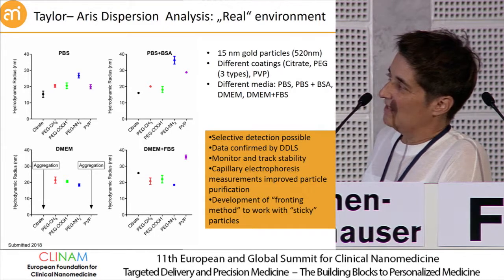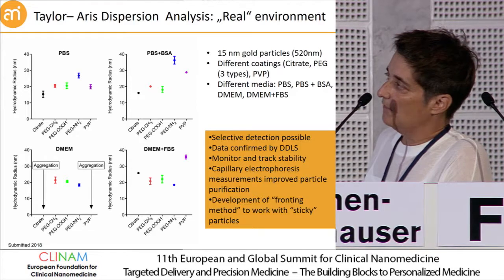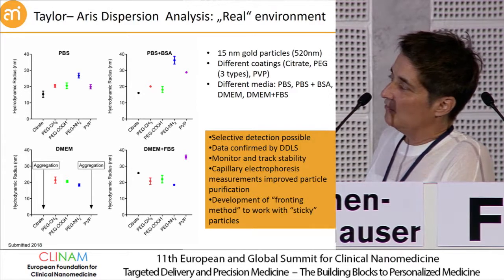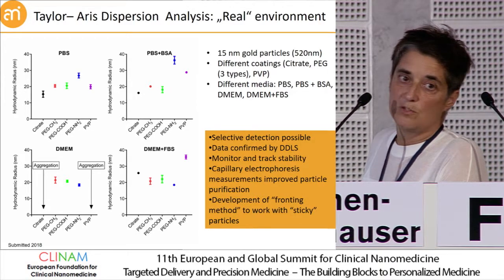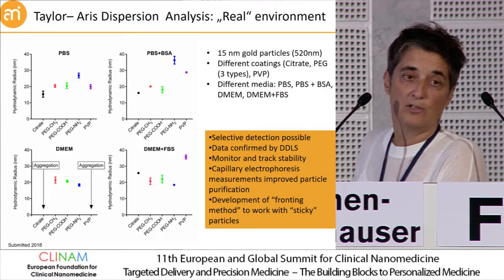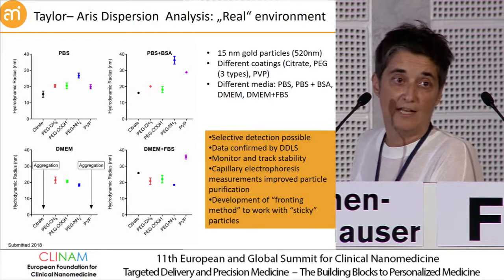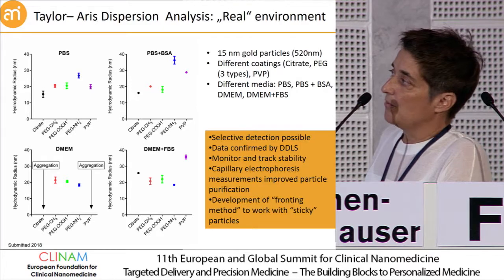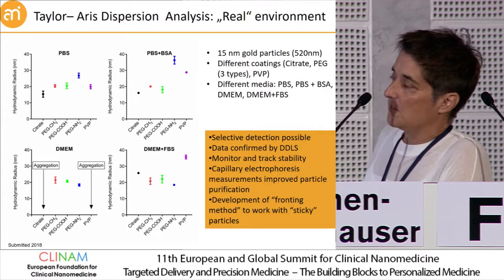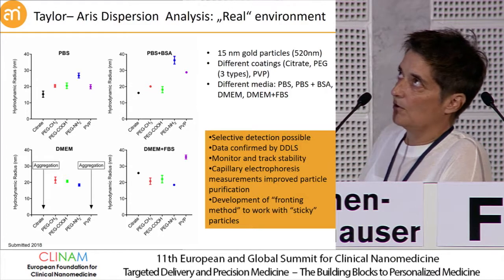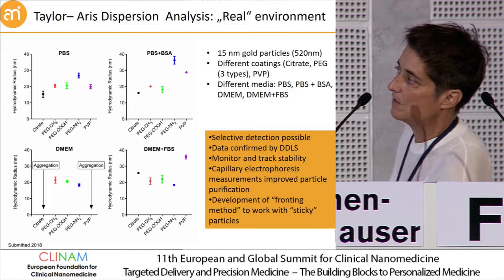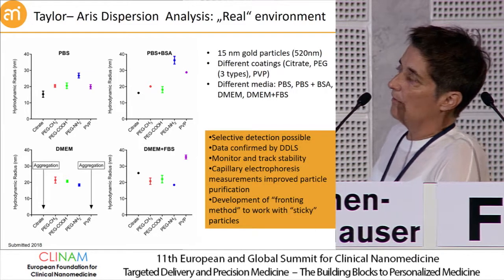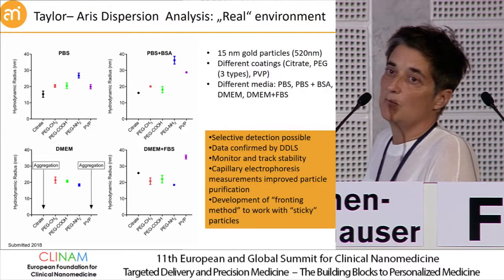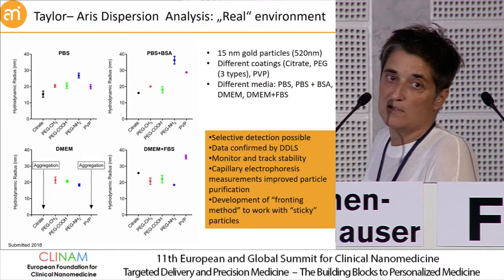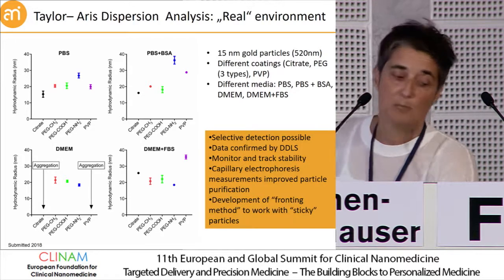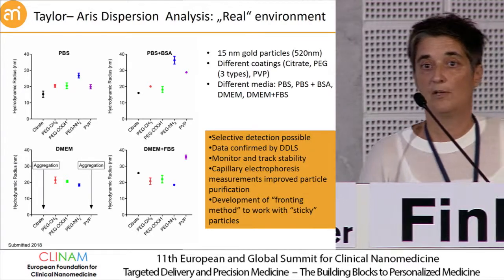You can track the stability over time, which actually works really well. You can selectively detect. There are 2 detection windows. You can also, for example, detect a particle and a fluorescent dye that you add on a surface. So you can also figure out how pure your sample is, or if what you grafted on the surface gets desorbed. And the only thing we are currently worrying about is that some of the particle suspensions are very sticky, so we need to modify the capillary in some of the cases.